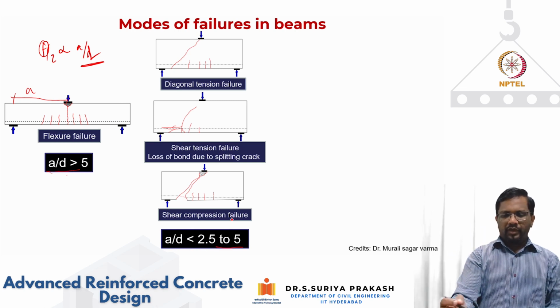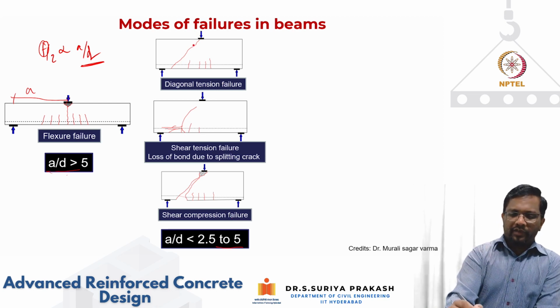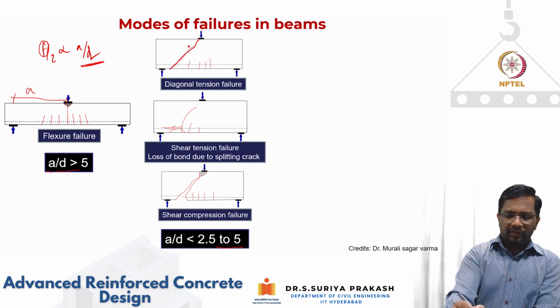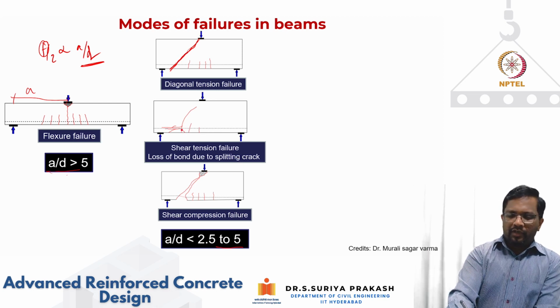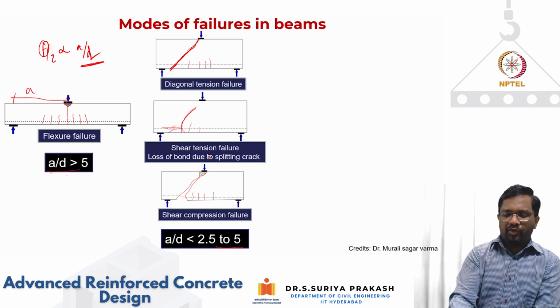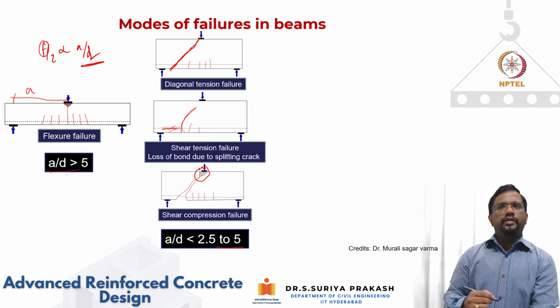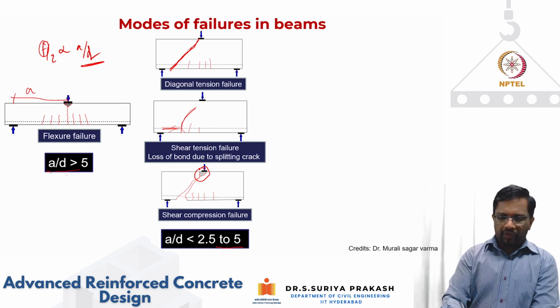When it is between 2.5 and 5, you will have different failure modes possible. Either you can have a diagonal tension failure, where your principal tensile stress exceeds the tensile strength of concrete, and you get this kind of nice diagonal crack. Or you can have a shear tension failure. You will have this kind of crack and then flexure, but the shear stress at the interface of the reinforcement can exceed your bond strength, and it can lead to this kind of splitting crack. Or you can also have diagonal compression failure, which is also called a shear compression failure.